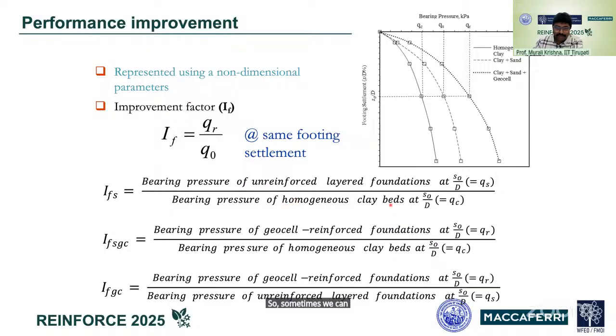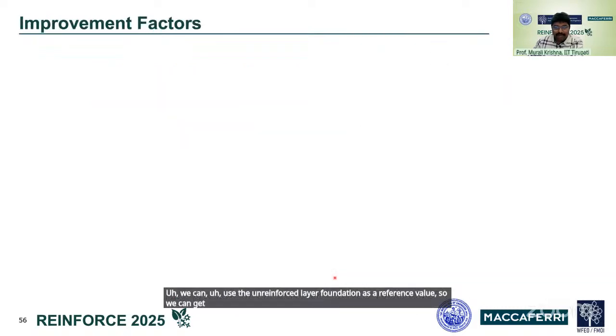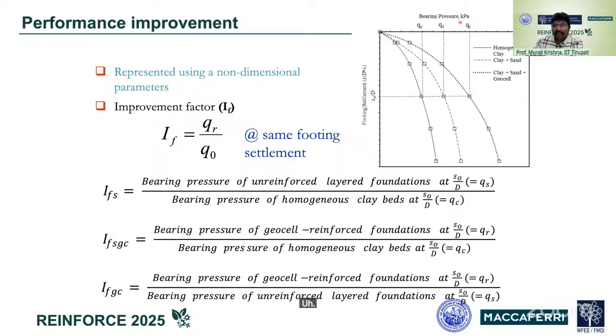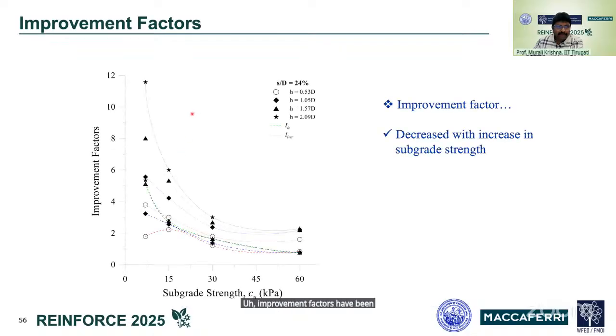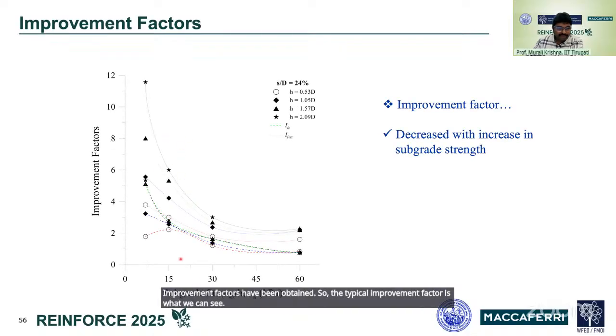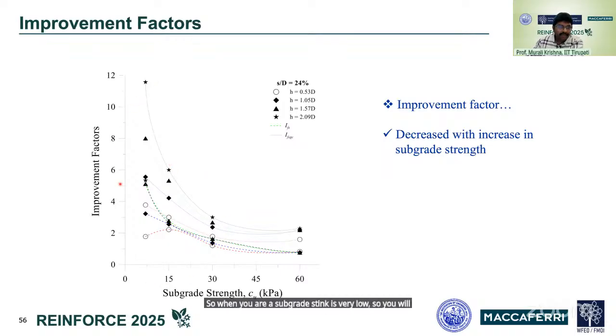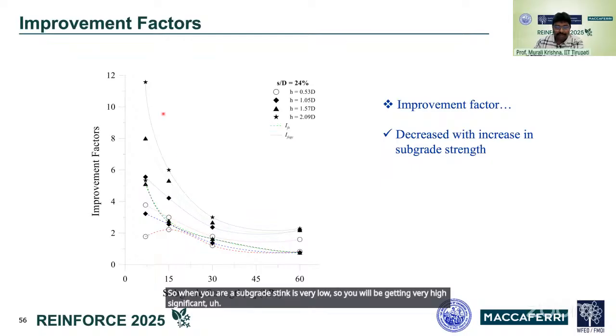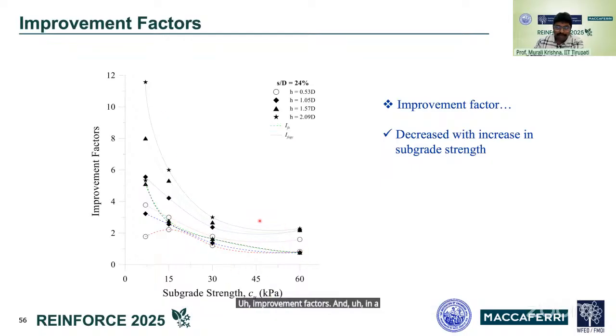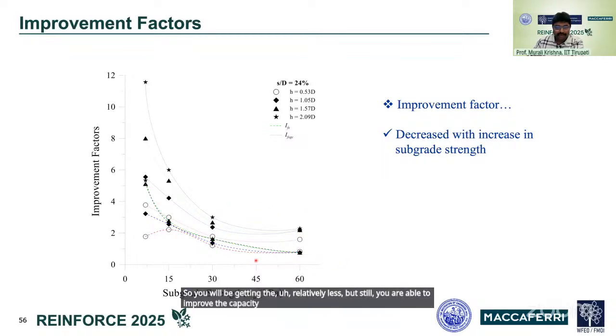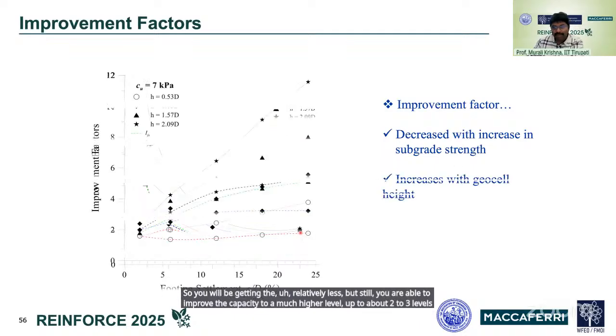So sometimes we can use the homogeneous clay bed as a reference, or we can use the unreinforced layer foundation as a reference value. So we can get the improvement level of different contributions with reference to the earlier explained parameters, either bearing capacity ratio or improvement factors. So the typical improvement factors, what we can see. When your subgrade strength is very low, you will be getting very high significant improvement factors, and in a moderately high subgrade strength, you will be getting relatively less, but still you are able to improve the capacity to a much higher level, up to about 2 to 3 times.